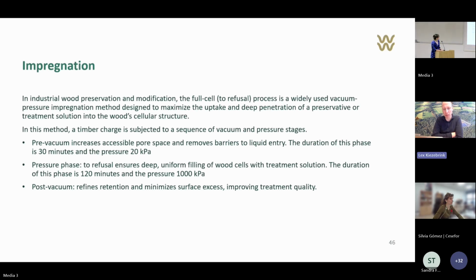The process itself, we didn't need to optimize a lot, because the main goal was to reach as high a retention as possible. That's why we applied this full-cell to refusal process. In general, when we optimize the impregnation process, we try to limit the uptake of impregnation fluid, but in this case we really need a high retention to get enough performance. So that's about it.